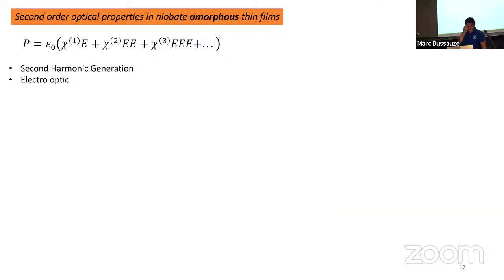So what about nonlinear response, nonlinear optical properties? To study it, the very simple way is to write the polarization equations like this, where you have the linear response with the chi1, which is linked to the refractive index, for example. And if the laser power is more intense, then you may have the second order optical response. But this second order optical response is forbidden in glasses because glass is amorphous and has an isotropic structure. Chi2 exists only in non-centrosymmetric crystals.